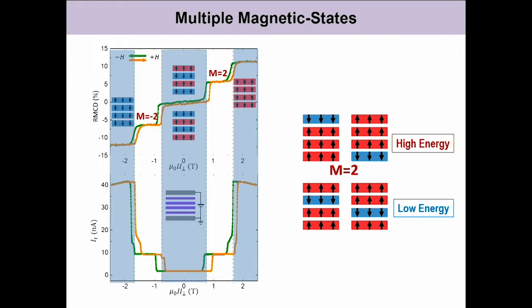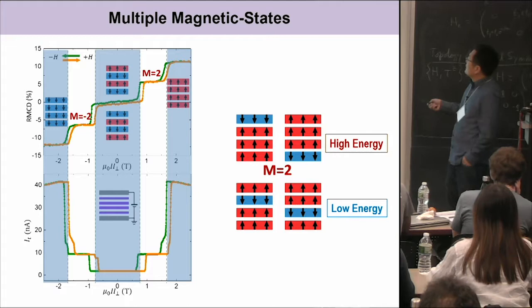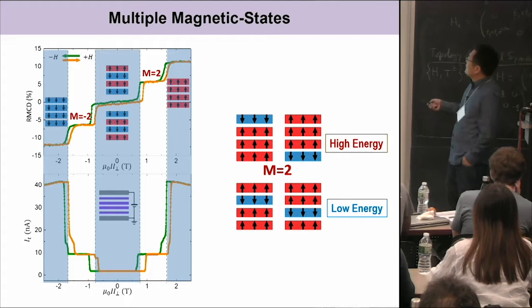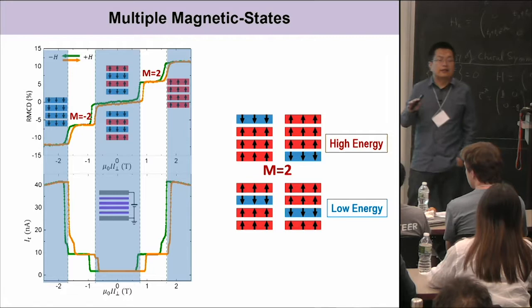I mentioned this example with tunneling junctions. We can measure the tunneling current as a function of magnetic field for a device with four layers, and we have these intermediate plateaus that show up. The correlation signal for the state with magnetization M equal to two corresponds to an intermediate state. For this magnetization M equal to two, there are four possible configurations, with one layer pointing down and the other three layer magnetizations pointing up. The key is this magnetic layer can be at the top, in the middle, or at the bottom.